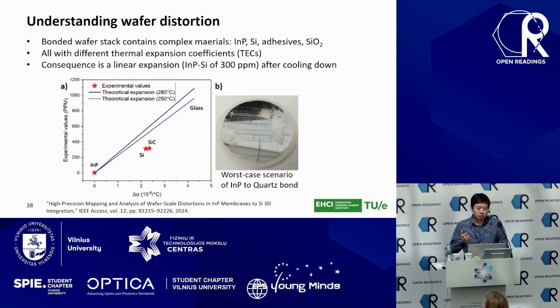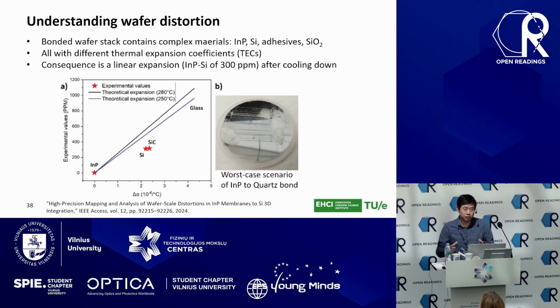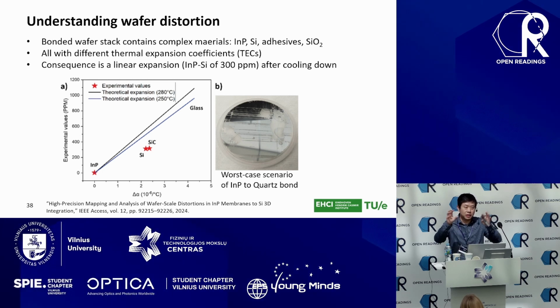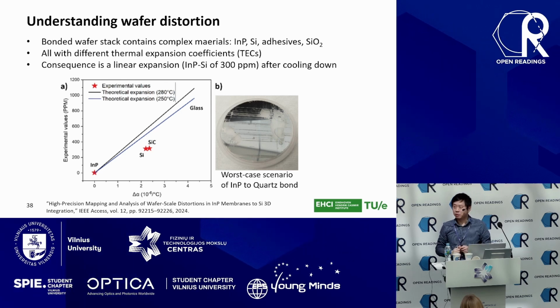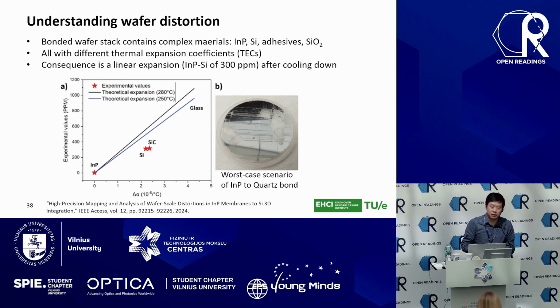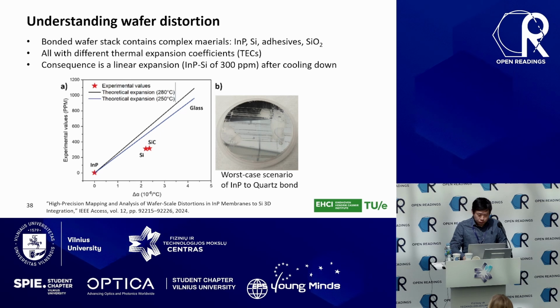But the thing is, the wafer scale matters because we are talking about 100 millimeter wafer size. If you multiply 100 millimeter by 300 ppm, it is about tens of micrometers. So at some location of your wafer, your originally made structure may jump to another location by tens of micrometers, which you don't really want, right? So that's why this quantification is very important.